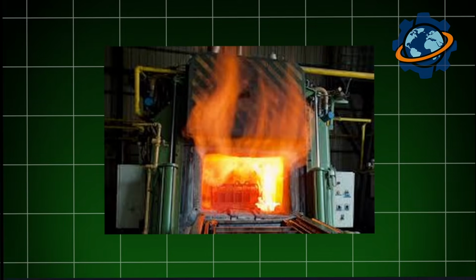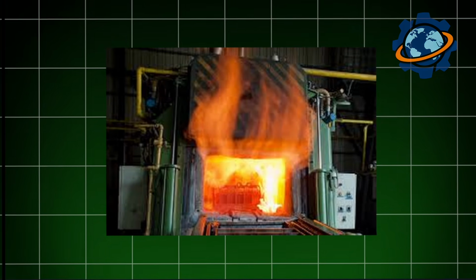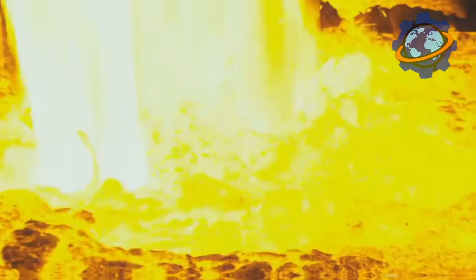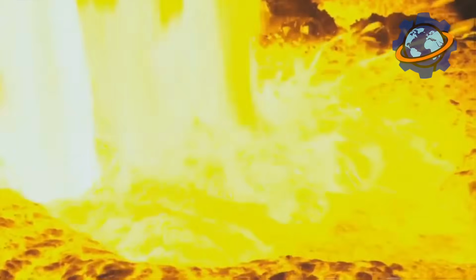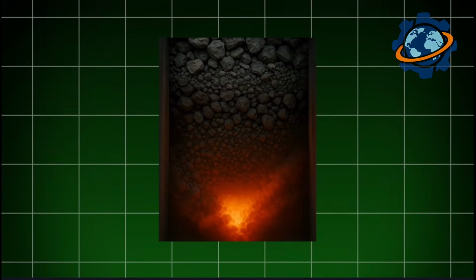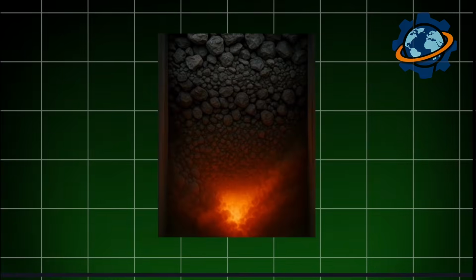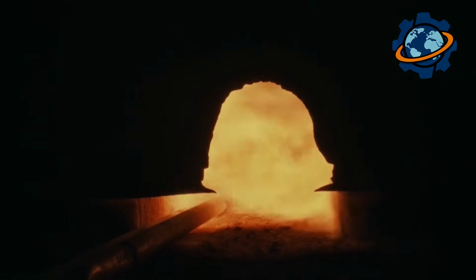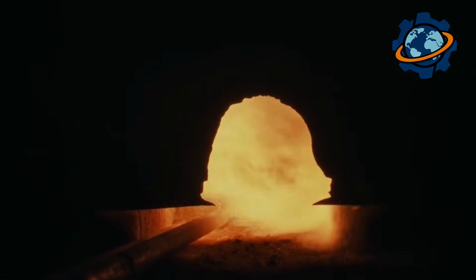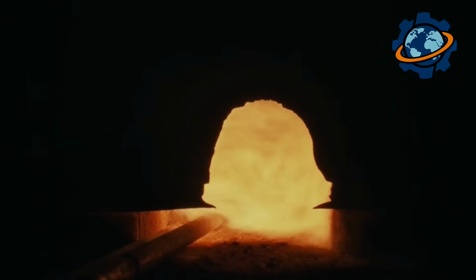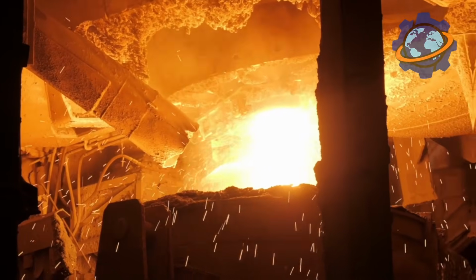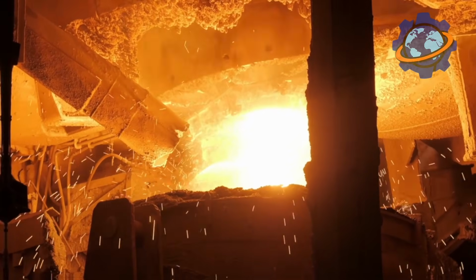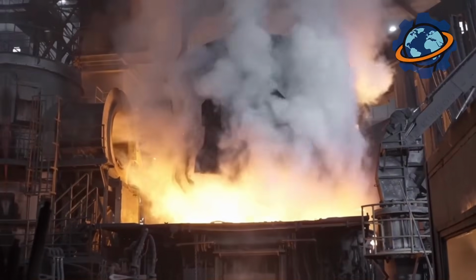At the plant, concentrate is loaded into fluid bed roasters, massive steel cylinders 66 feet tall. Hot air under pressure is blown in from below. The concentrate powder lifts up, floating in the air like dust. Gas burners are ignited. Temperature rises to 1,650 degrees Fahrenheit. The zinc sulfide ignites. Yes, the ore burns.